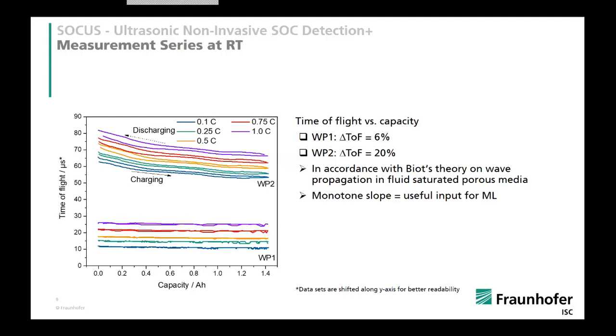For the discharging, however, we see two effects. One, we have a hysteresis between charging and discharging, and second, the slope is dependent on the C rate. You see that the 1C discharging has a higher slope than the 0.1 C rate.